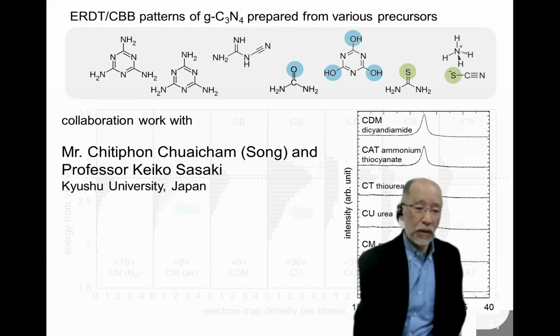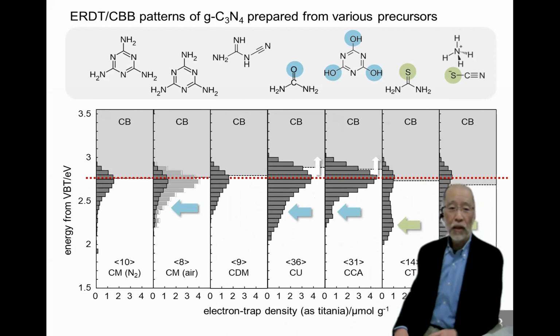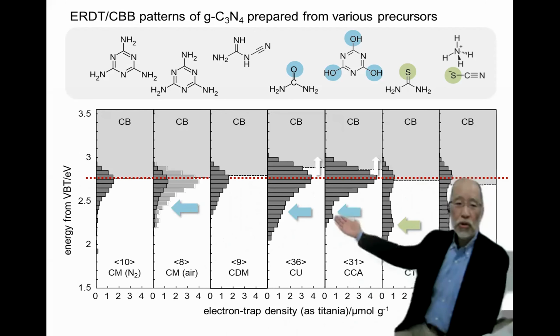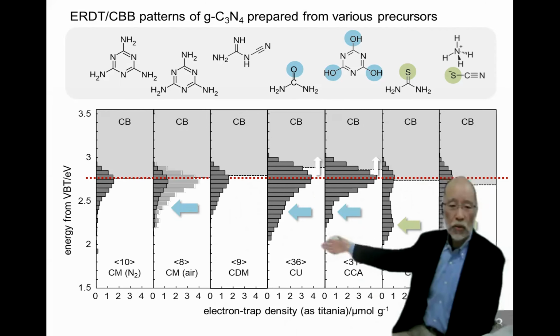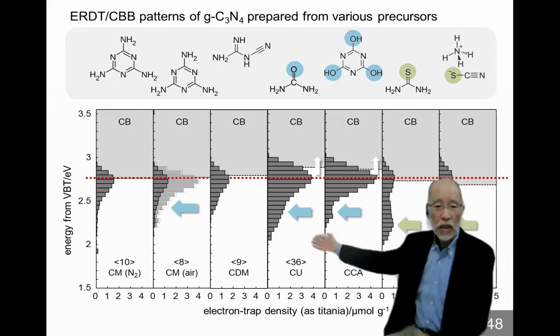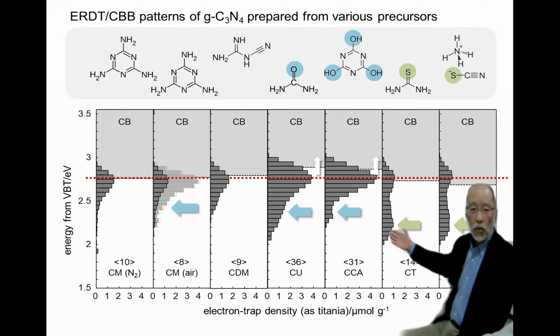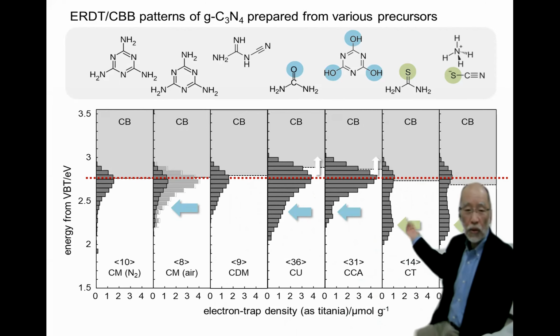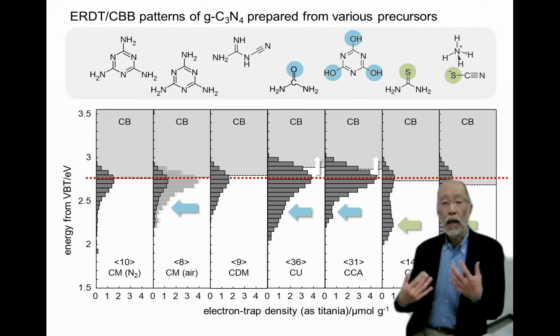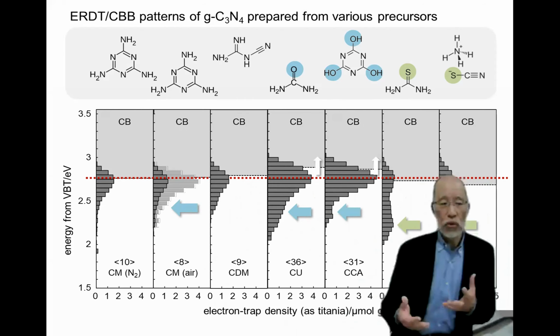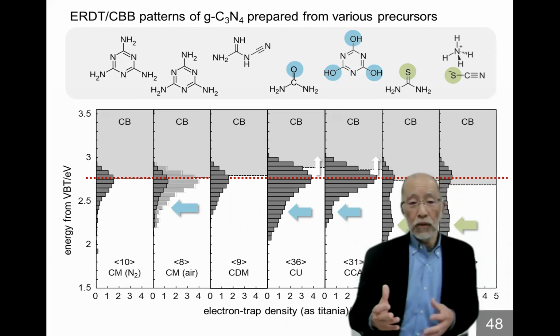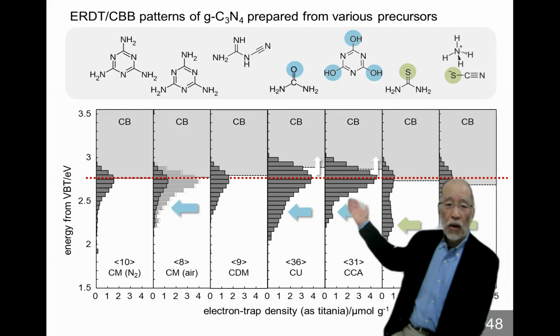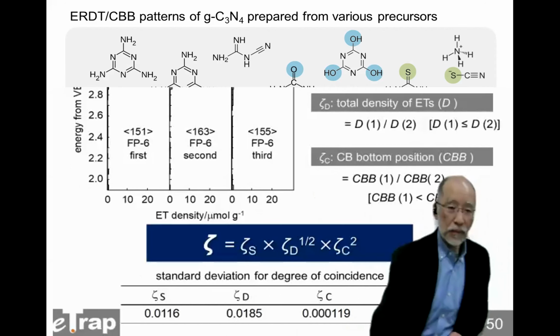And by checking the ERDT/CBB pattern, it is clear that the oxygen-containing precursor gives lower energy peaks, and the sulfur-containing precursor gives even lower energy peaks. And this is due to surface doping with those heteroatoms, oxygen or sulfur.